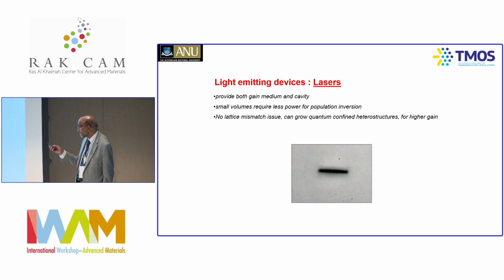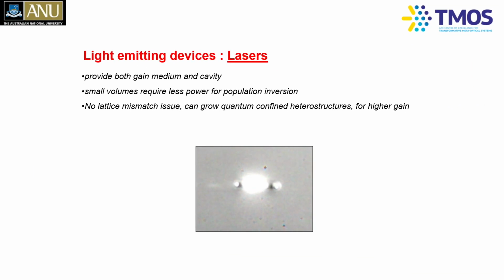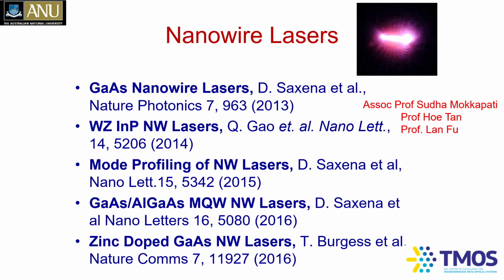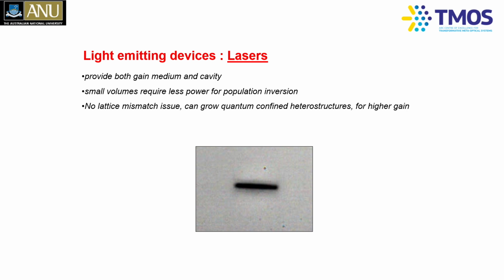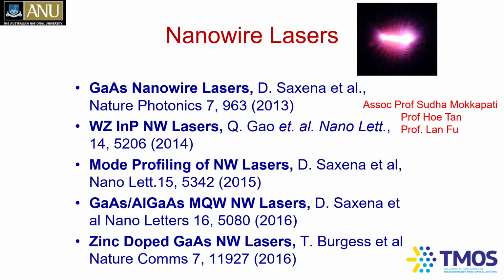But it turns out, if you take a nanowire, the nanowire acts like a gain medium, and both ends of the nanowire act like a mirror because of the refractive index difference. So naturally, they form a laser cavity. I don't have to do anything of trying to put the mirrors or anything. And if I pump this nanowire, with the right dimensions, the light starts propagating along the length of the nanowire, and if you get this right, you can get the lasing to take place. We've been working in this area for a long time, and we demonstrated a wide variety of nanowire lasers by different students. But I'll not have time to go into the details of all of them, and I'll share with you one or two examples.